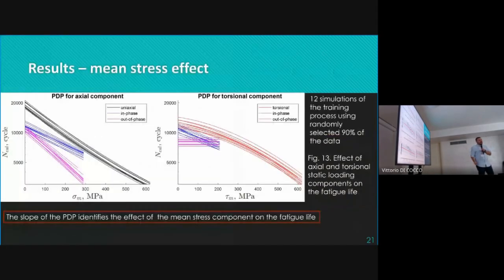It will be seen better on this slide, because these are all the 12 cases we did to calculate the MAVE, 12 different approaches. Some are a bit higher or lower, but you can still see the trend for each of the 12. For the uniaxial, it is the black one. On the left is the axial component, tension-compression. On the right side is the torsional component. On the left, one of them goes down faster, the second one slower, but there is an impact. On the right side, for in-phase, the blue lines, you can clearly see the impact, and it's even higher than in the axial, in the just torsional case without tension-compression. But the magenta line, probably magenta, clearly has no impact here.